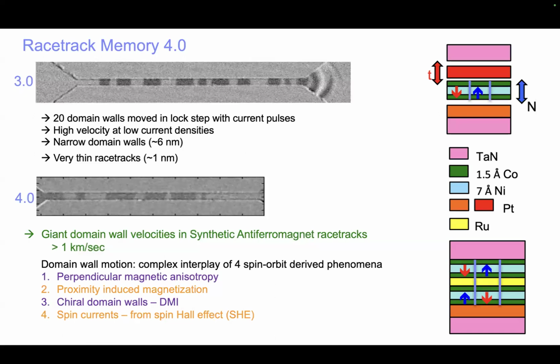You could, for example, imagine using a scanning near-field optical microscope. We actually have one, which has an optical resolution of 20 nanometers. However, that technique doesn't preserve the polarization of the light. So it's very difficult to detect magnetic structures, maybe not impossible. But to date, optical techniques, as you said, you can reduce the wavelength, but it's still restricted to, let's say, a few hundred nanometers. So I'm going to tell you how we can do this using integrated devices for reading them. That's what I want to briefly discuss next. So it's not possible optically, it seems, maybe SNOM in the future.